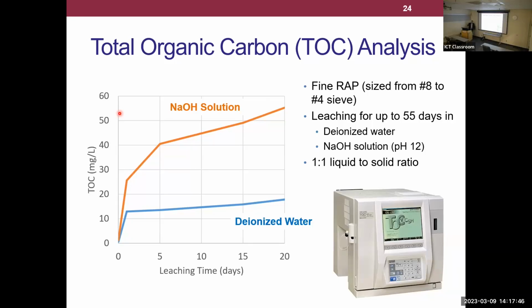After a couple of days, every few days, we would take a sample out and send it to a TOC analyzer, total organic carbon. In this technique, you basically inject your aqueous solution, it goes through some sort of flame ionizer, and it tells you how much organic carbon is there. It doesn't detect, for instance, CO2 dissolved in the water. That's not organic carbon. The organic carbon would be things in organic molecules, for instance. Asphalt is made out of organic molecules. So what we found is that in the sodium hydroxide solution, we are definitely leaching a lot more organic compounds than we are in water. So that's our first suggestion that maybe this hypothesis starts to make sense.